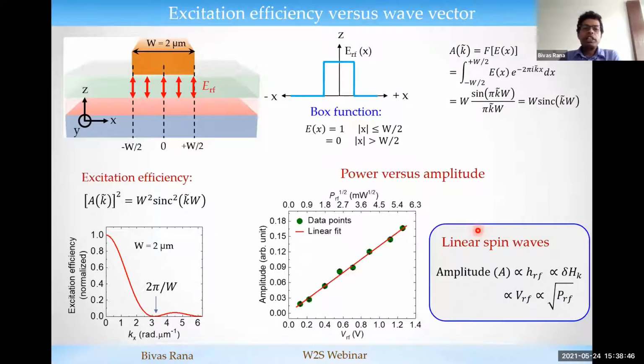So now, what is the K vector we can excite by this method? To find that out, we need to do the Fourier transform of the electric field. The electric field underneath this gate electrode can be expressed by this box function, and if you do the Fourier transform, you get the sinc function. The square of the sinc function gives the efficiency of excitation of the spin wave as a function of the wave vector. This shows that as we increase the wave vector, the excitation efficiency is significantly reduced, and it becomes almost zero at the K vector equal to 2 pi over the width of the top gate electrode. So if you really want to excite spin waves with a very short wavelength and a very high K vector in an efficient manner, you must shrink the size of the top gate electrode.